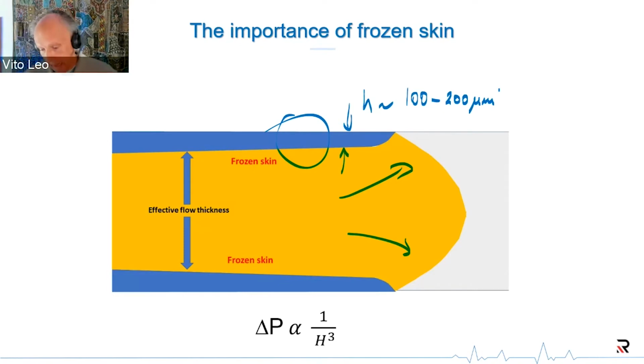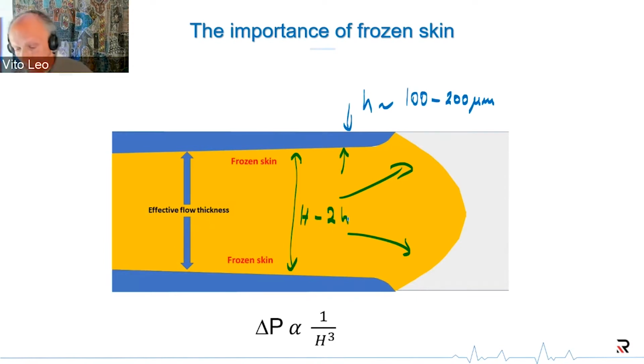But if you're trying to make a part of 1 millimeter thickness, or maybe even lower than that, then you have a substantial effect of this reduced effective thickness, because obviously if we start looking at the effective channel for flow, it's going to be the nominal thickness minus 2 times the frozen skin.